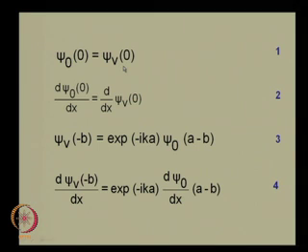So simply using the solutions, if you do these equations, we will come up with two equations corresponding to these two. Similarly, based on periodicity, the value of the wave function on one side at a particular location should be this term times the value of the wave function at another location, again coming from one side where potential is equal to 0 to another side where potential is v. And the same thing for the slopes on either side, with this factor thrown in, should work out to be the same. Okay, so this is how we have got these four equations, and they directly relate to the system that we have just described.